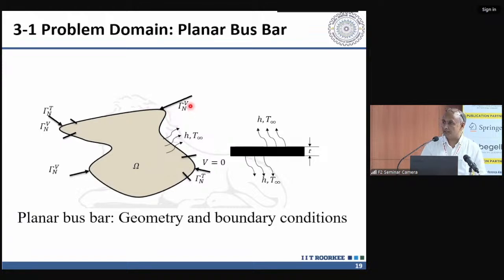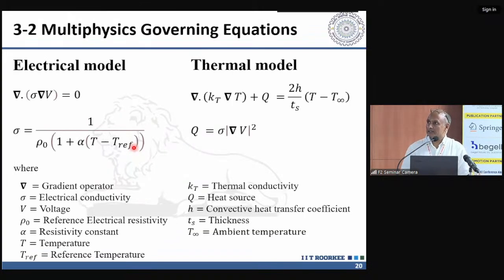Here the superscript V represents the electrical problem, the voltages, and T represents the temperature. So in the same geometry, I have tried to put boundary conditions of both of them. And this is our model. For the electrical model, we are solving what we call the electrical continuity equation in terms of voltages. So divergence of sigma gradient of phi, where phi is the voltage or potential, and sigma is the conductivity, and we know the electrical conductivity is very sensitive to temperature. We have taken a linear variation of resistivity. So rho 0 is the resistivity at the reference temperature, and we have taken a linear temperature dependence. That's how sigma is related.